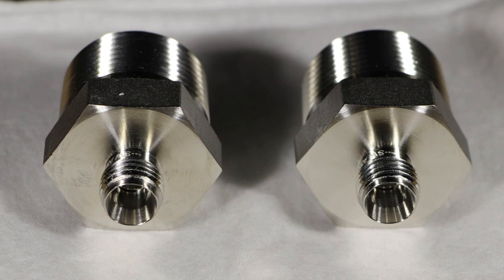The inert surface layer, termed the native oxide layer, is usually an oxide or a nitride, with a thickness of a monolayer of 0.1 to 0.3 nanometers for a noble metal such as platinum, about 1.5 nanometers for silicon, and nearer to 5 nanometers for aluminum after several years.